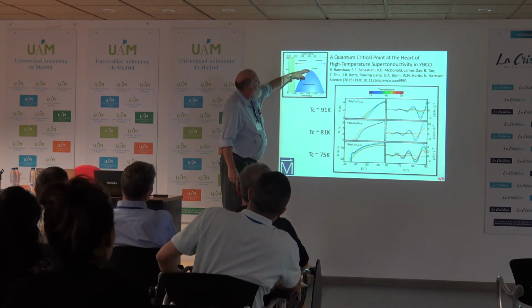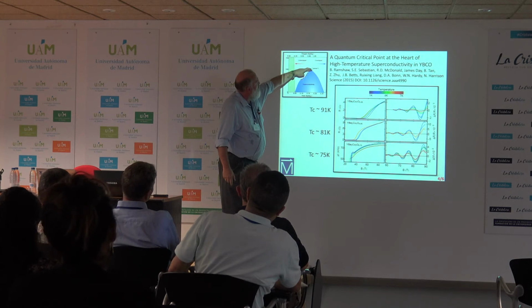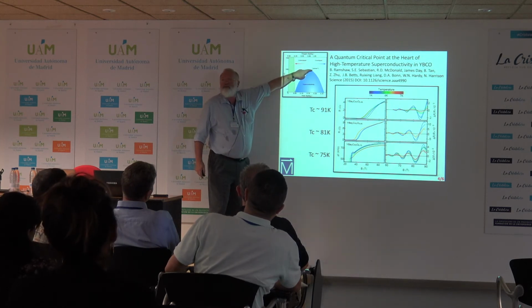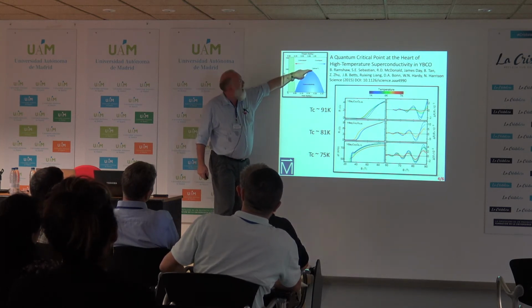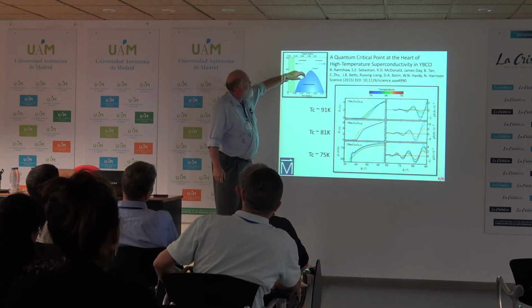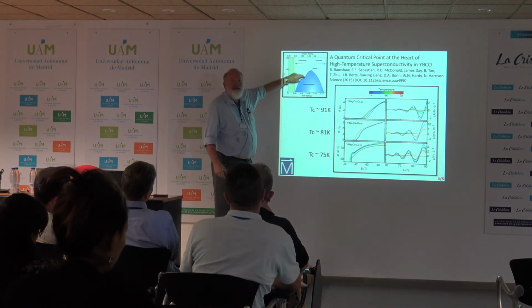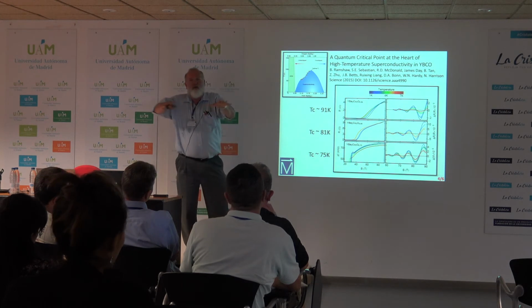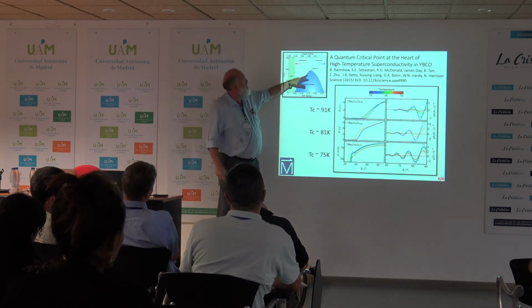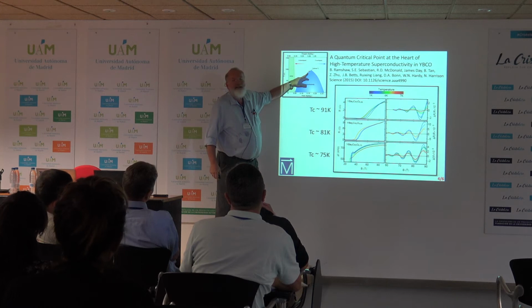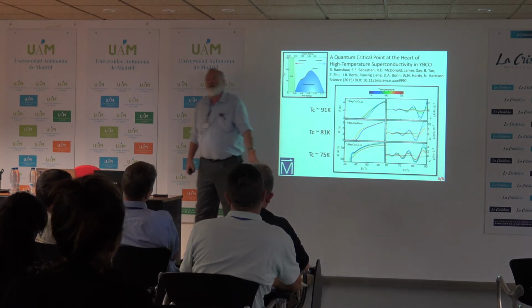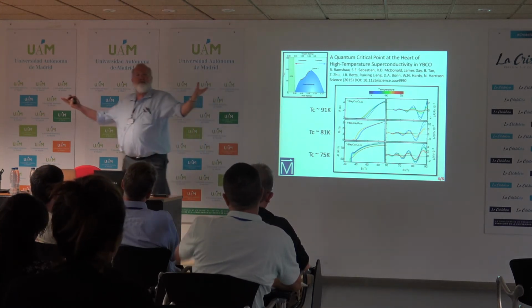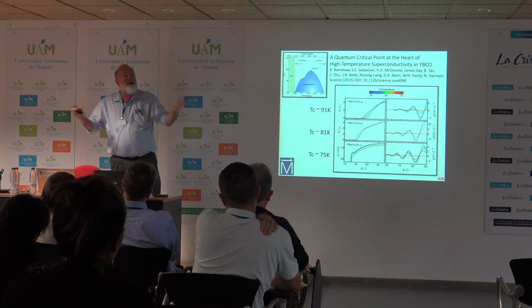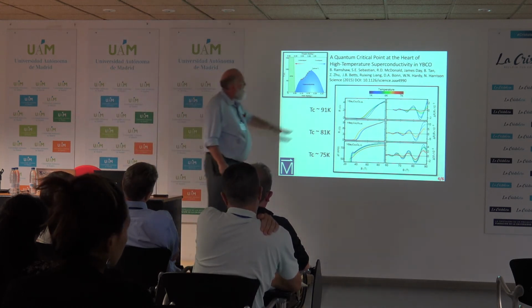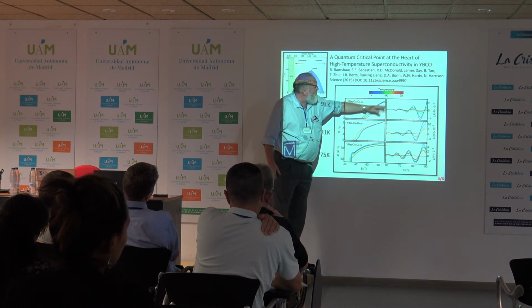As you move in this direction, Brad Ramshaw realized you're getting close to 0.7, which is another stoichiometric point where you should have high degrees of order. And so they changed the entire philosophy. Rather than annealing the samples to get the oxygen to order, they realized that the best thing to do here is, since you've only got a few point defects, quench cool the samples so the oxygen just freezes out rather than puddling up. So that allowed them, for the first time, to be able to see quantum oscillations.